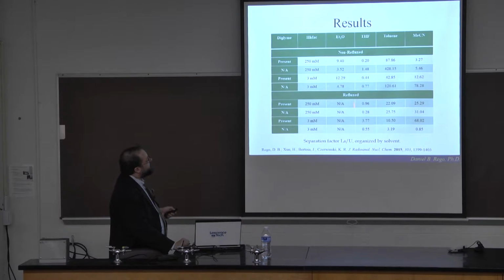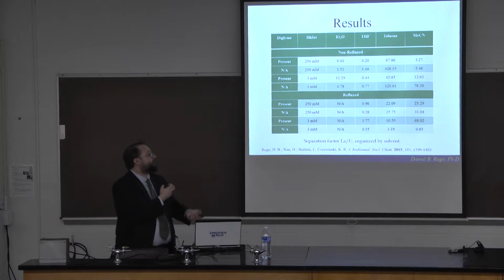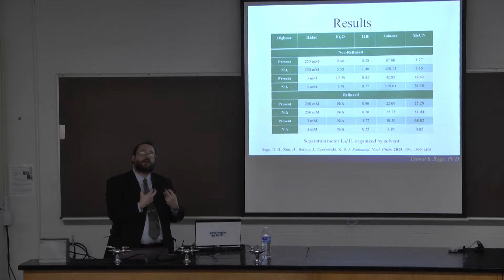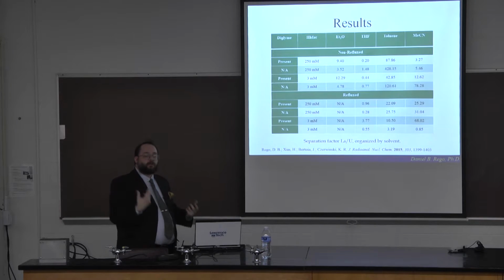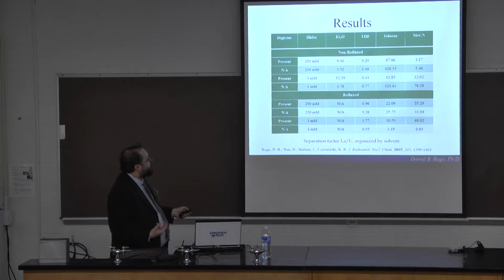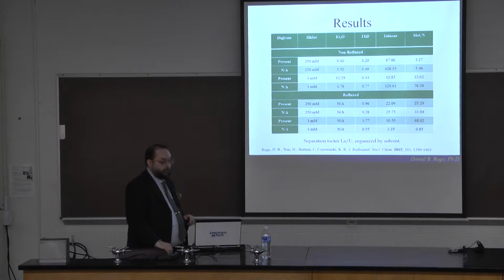While with other solvents such as THF, that kind of reverses itself, and I'm actually preferentially extracting out the uranium. So simply by changing the solvent, I can completely change the profile of the extraction. So it's a very fine-tunable process here. And this was actually recently published in the Journal of Radioanalytical and Nuclear Chemistry.